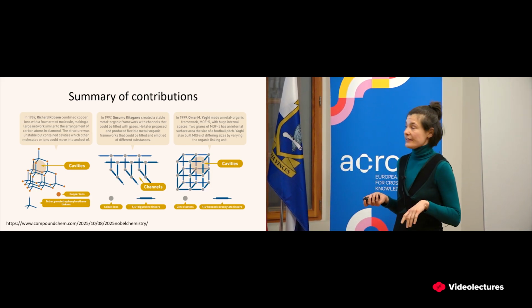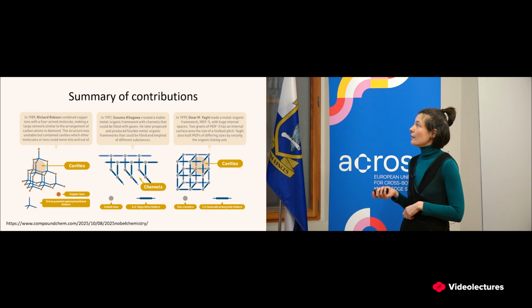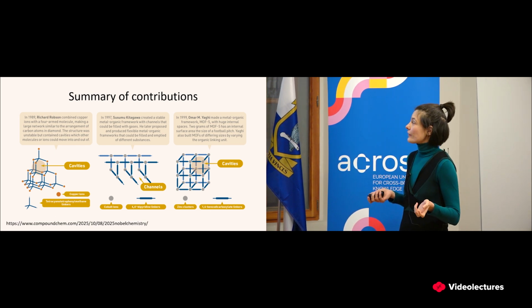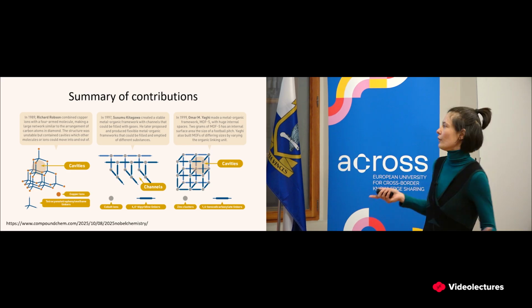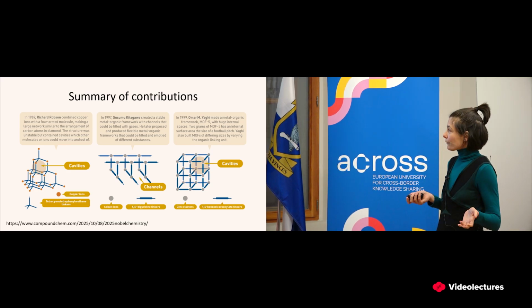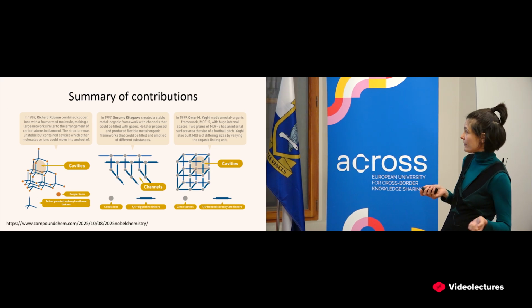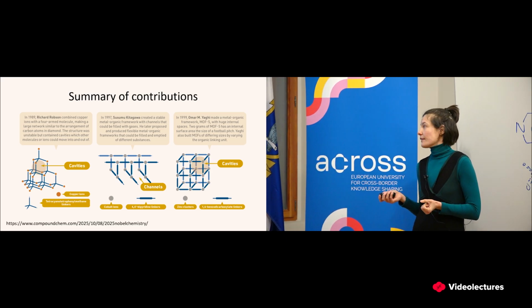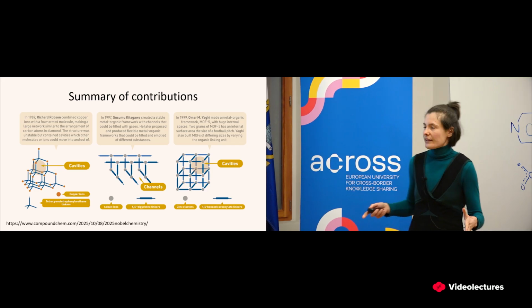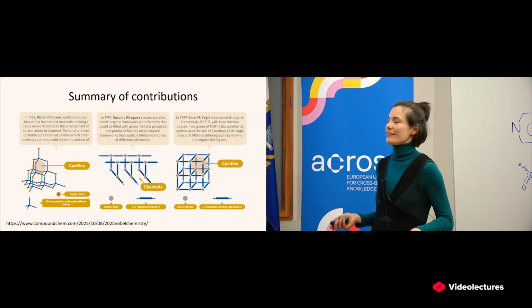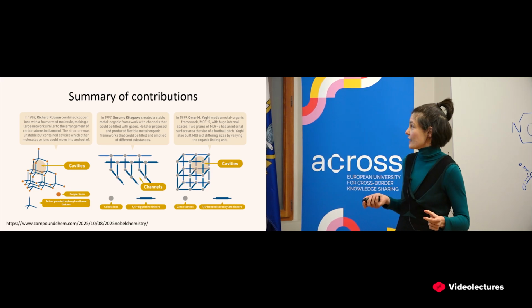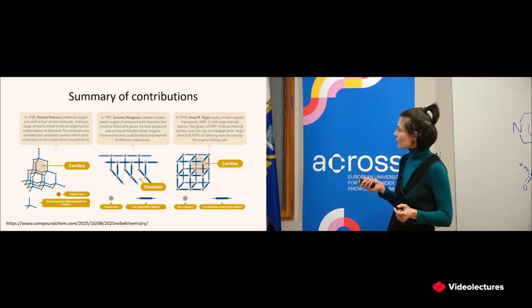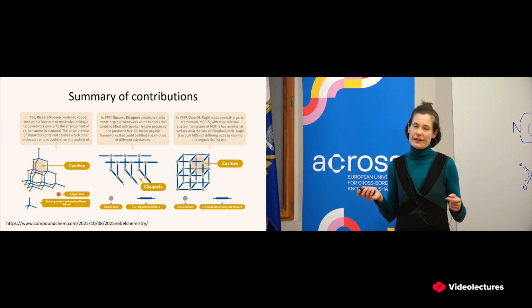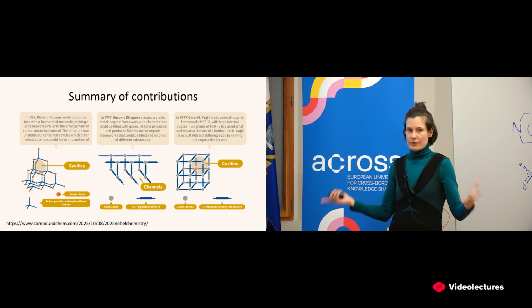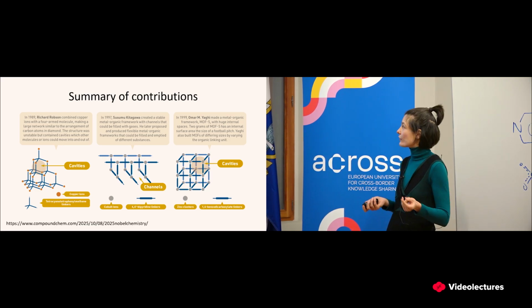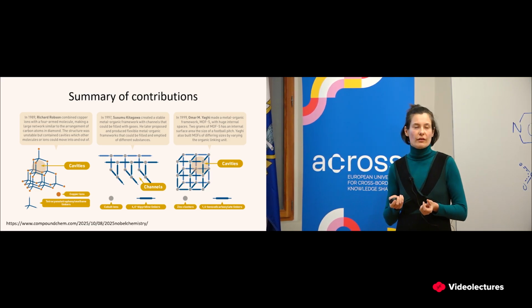Later, in the 1990s, Professors Kitagawa and Yaghi continued this work, and Professor Kitagawa made his two most significant contributions: making a material which has channels and not just cavities, and also demonstrating that these materials can have a soft nature. So depending on what gas they contain or do not contain, their shape can change. And then lastly, we have Professor Omar Yaghi and his famous MOF-5 that I was just speaking about. So materials with really high pore volumes, high surface areas, and then also the MOF families.